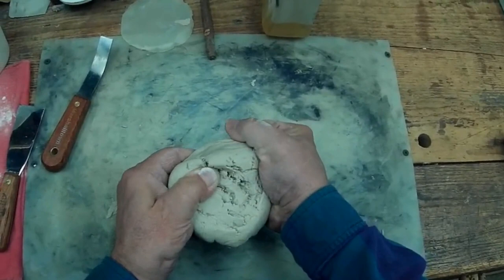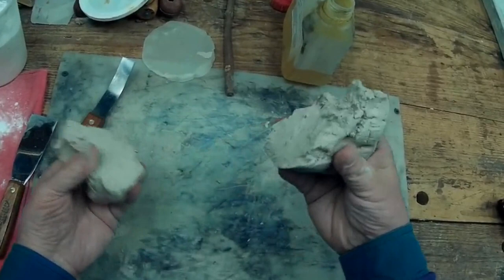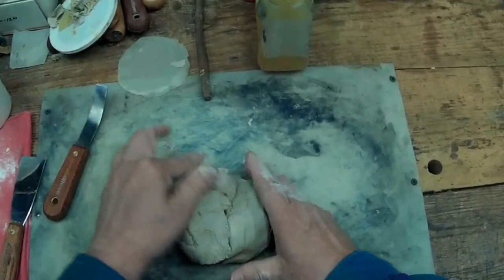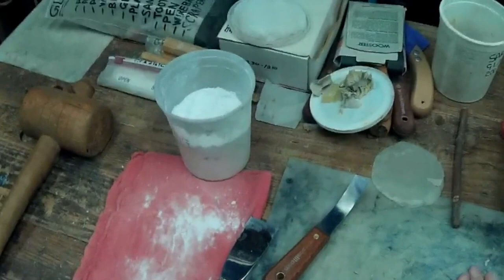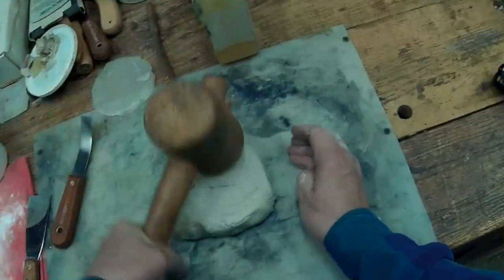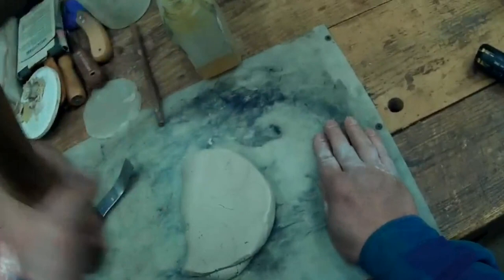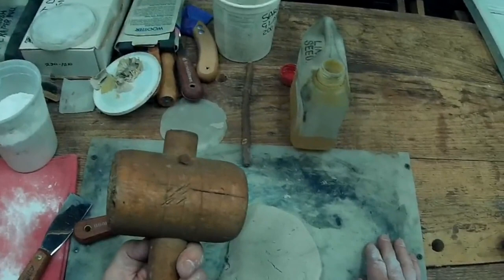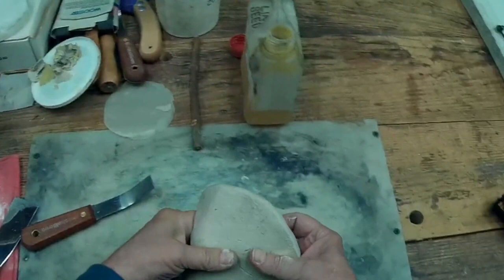It's a little short — by short I mean it pulls apart and doesn't stretch out — might be a little shy on oil. So I think I'll knead that up. One traditional way to knead putty is with a mallet, a putty mallet. I learned about the putty mallet in an 1870s trades manual that was talking about mixing up your own putty.